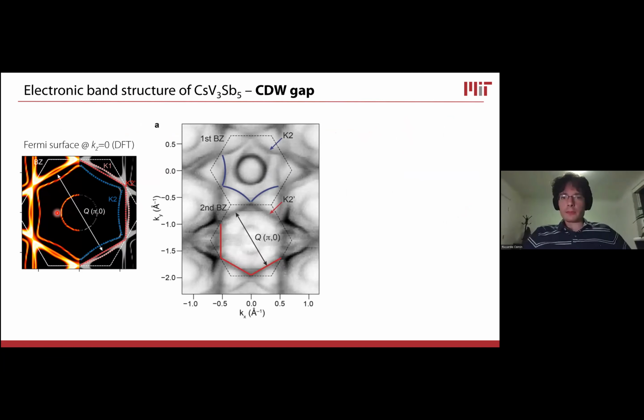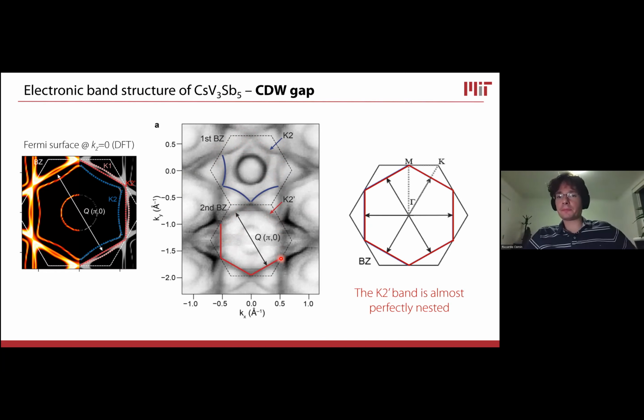And we see this experimentally also very clearly if we look at the Fermi surface. We see these bands that have this Fermi surface, which has this hexagonal shape. And this hexagon is a little bit warped for this K2 band, this blue band. And instead, it's a much straighter hexagon for this K2 prime band. So potentially this K2 prime band is actually one that has good conditions for nesting.